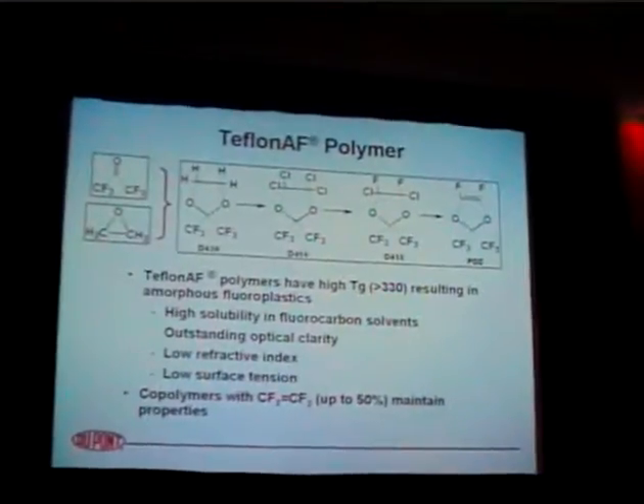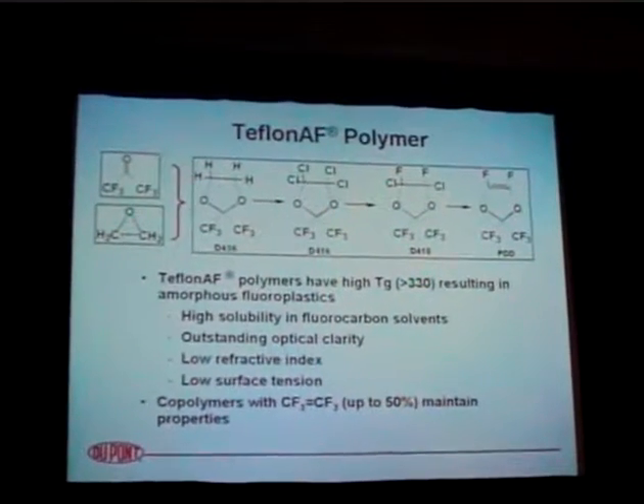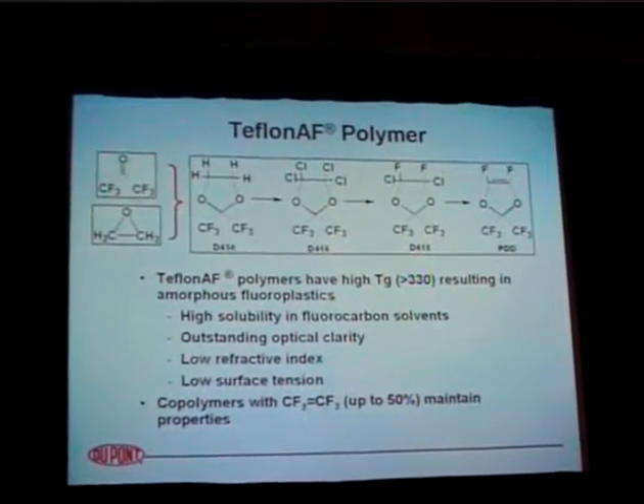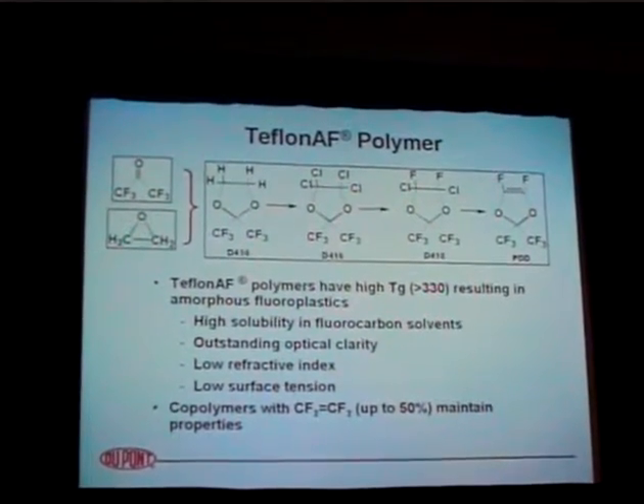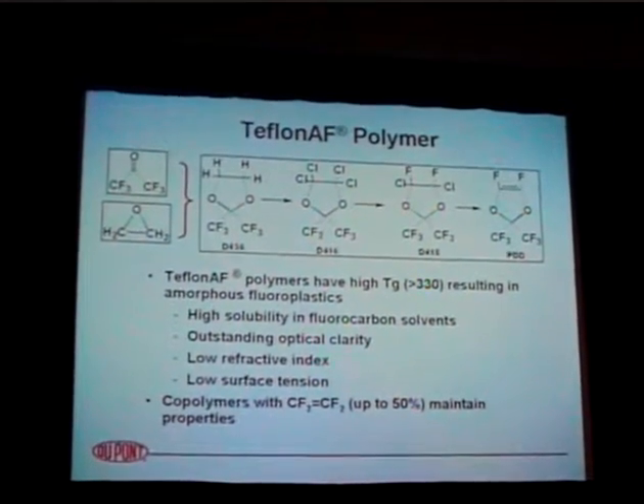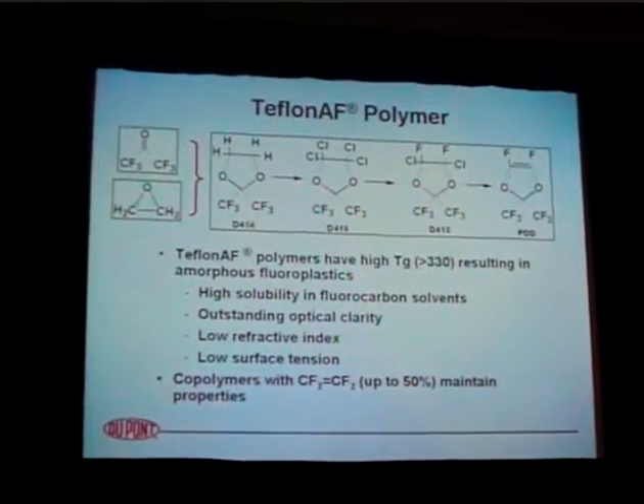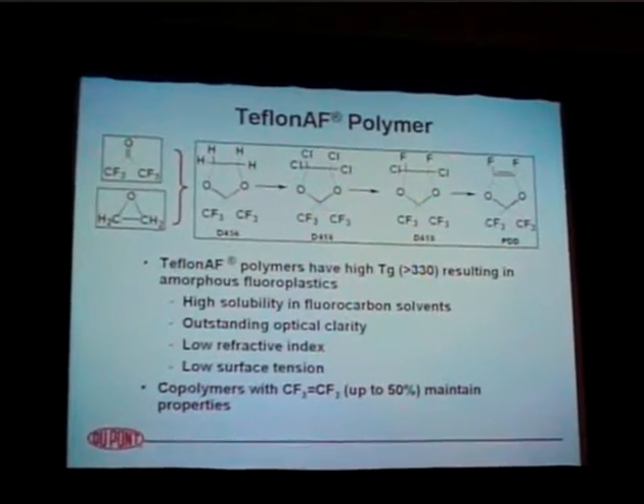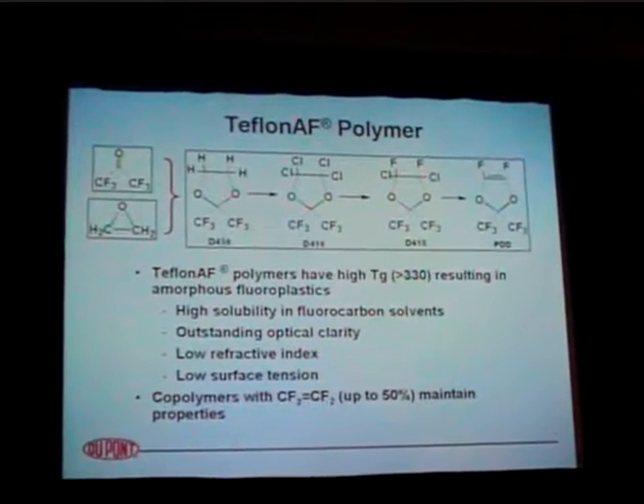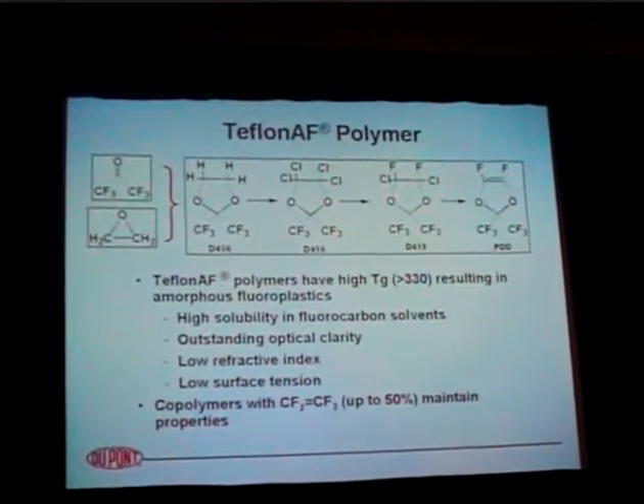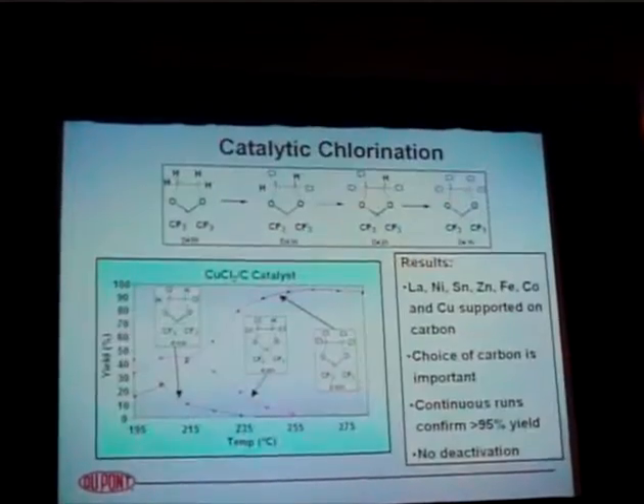And it's extremely reactive, and the reason the catalysis that I'll be talking about is so difficult is that a trace amount of acid causes that material D436 to zip right back to hexafluoroacetone. So with the main catalysts that you look at for these reactions, all you see is hexafluoroacetone coming out of your GC. So it's important to get the right supports and the right catalyst.